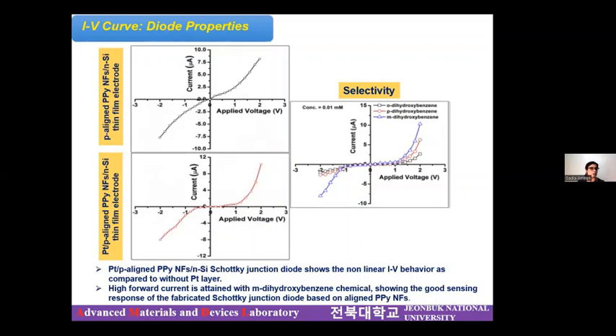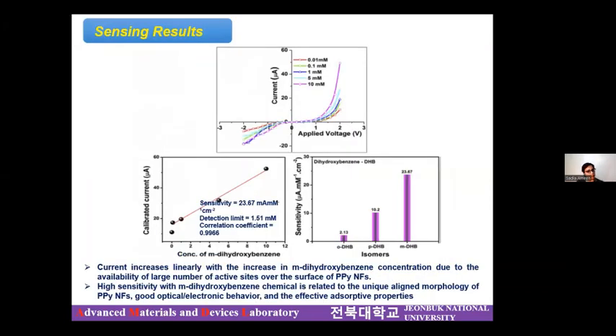And this is the interesting part of the work, that is, the sensing part. Here we have made a diode. When we take just the PN junction, that is, the aligned polypyrrole over the surface of the N-type silicon, the nature of the current is symmetrical, which means the current increases linearly in the forward as well as in the backward direction. However, when we deposited the Pt electrode on top of it, suddenly the nature of the current changed and it shows nonlinear behavior. That means it may be because after the deposition of the Pt, it has created Schottky barriers between the polypyrrole and the silicon substrate. And these are some of the sensing parameters that we obtained through the experiment.